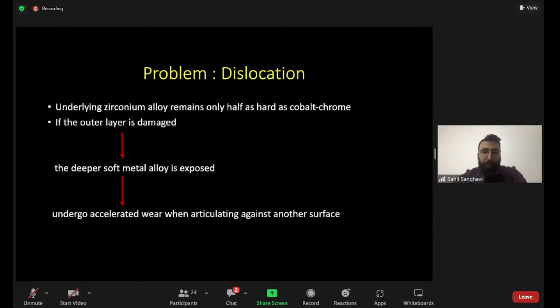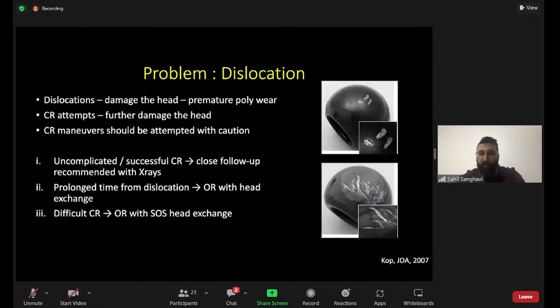The problem, or the practical implication here, is of dislocation. So if you have an Oxinium head which has got dislocated, the outer layer can get damaged and undergo accelerated wear, as you can see in these images. So if you have a dislocation with an Oxinium head, how do you tackle this? If you get an easy closed reduction, you can get away with it. But if you have a complicated closed reduction, you will have to follow up these patients closely with serial X-rays to look for wear. If there is a difficult closed reduction, it's better to go in for an open reduction where you can examine the Oxinium head and you may have to be ready with performing an exchange of the head.